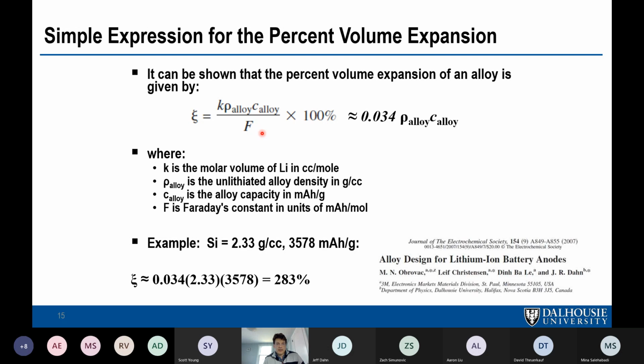And for silicon, where K is exactly equal to 9, then you can work out that this expression is this simple quantity here. So as an example, I put in numbers for silicon, and 0.034 times the density of silicon times its gravimetric capacity gives you 283% volume expansion. And the exact number is 280. So this is a very close approximation.